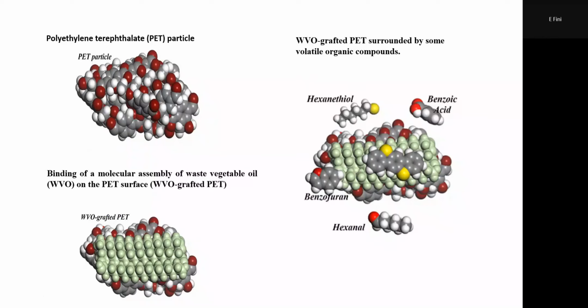Well, one reason is oxidation, which we always look at, how the oxidation happened. But another reason is some of the components in asphalt are going to air as volatiles. So they're gone, they're lost. And that contributes to aging. So more and more compounds of asphalt, which are supposed to be inside asphalt, go out and they leave the asphalt weaker. As a result, it becomes more prone to cracks and degradation. So what happened here, with this plastic, now they are keeping it in because of a good interaction between them. They don't let them evaporate or emit to air.